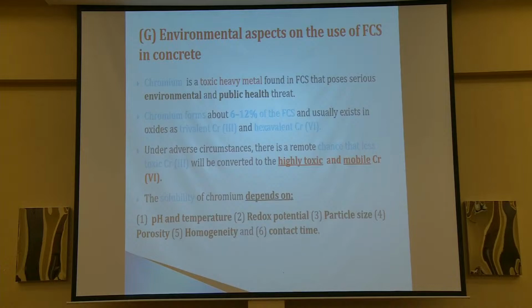And also, my final remark here is we need to take care also of the environmental impact of these materials in the environment. And therefore, for ferrochrome slag, for example, we need to check the heavy metals. We need to conduct leachate tests for the raw material and also for the binder. We need to see if there is any leachate, if there are any heavy metals that cause harmful effects to human beings. And also, we find that in ferrochrome slag, we have the chromium oxide, which is hexavalent chromium (Cr VI).